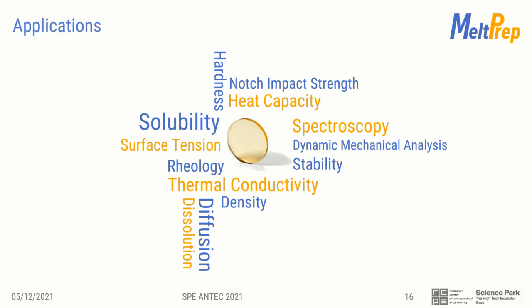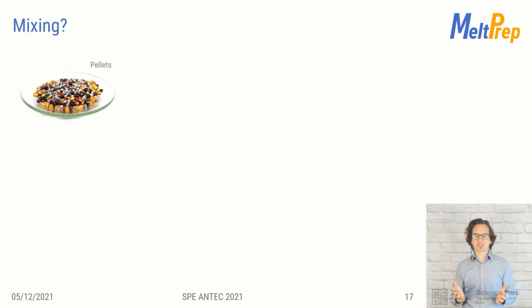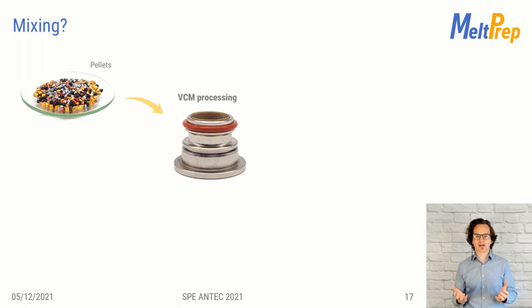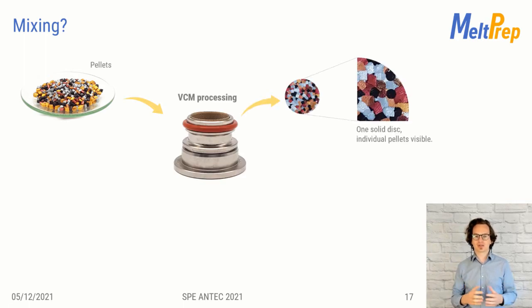Unlike an extruder, VCM does not mix mechanically. With vacuum compression molding, you only compress and melt the material. To illustrate the mixing mechanisms, we have prepared the following examples. If one puts multicolor pellets into the sample chamber and runs the VCM process, one will obtain a disc without any air inclusions. But you can see the phase boundaries between the individual particles. There are no shear forces and there is no macroscopic mixing.